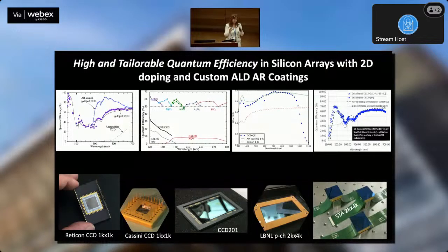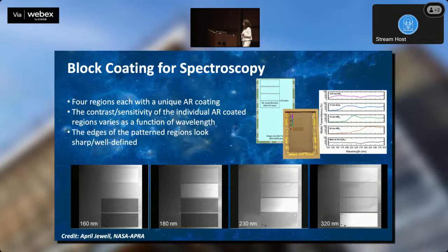The 2D doping, the nanoscale engineering that we do with MBE, gives you 100% internal quantum efficiency, which means you're limited by reflection only. Now we use atomic layer deposition to make these custom coatings and tailor the response that we want. And here I'm showing some that are 60%, 80%, 90%, depending on the range that we were designing these for. And ALD actually has been a real godsend because of its atomic layer by atomic layer control and arbitrary scalability to larger arrays. It's a really useful tool, and we have put it to really good use. In fact, it has also enabled other innovations that I will get to in a minute.